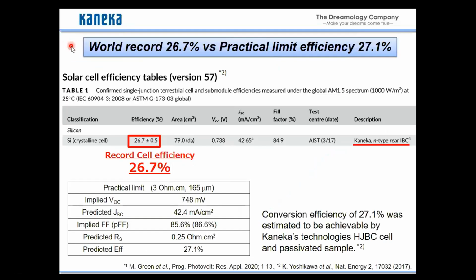And finally, we reached an efficiency of 26.7%. So this is noted as a record efficiency of crystalline solar cell in the efficiency table like this. Maybe you may think that this update of efficiency from 26.1% to 26.7% is not big. But based on our result, we estimated the practical limit of efficiency, and it was 27.1%. Since we are almost close to the limit, it was very difficult to get a small update.